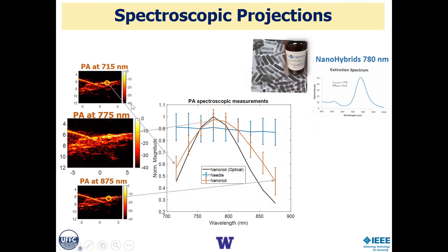Okay, and in this case, we can see that that spectrum closely matches the spectrum of a nanoparticle, which we injected as a contrast agent. So we know that this pixel is dominated by the contrast agent. However, if we look at this other pixel up in this area, which is where the needle alone is, we see a completely different spectrum, which corresponds to the needle spectrum. This is molecular profiling with optical spectroscopy.